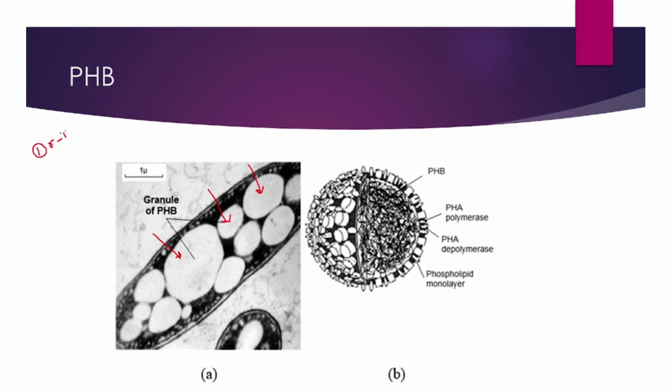You make the recombinant DNA and insert it within the chromosome of E. coli, which when transcribed and translated produces these PHB granules. And second, you inhibit the PHB depolymerase enzyme. These two things are necessary in order to get better yields of PHB.